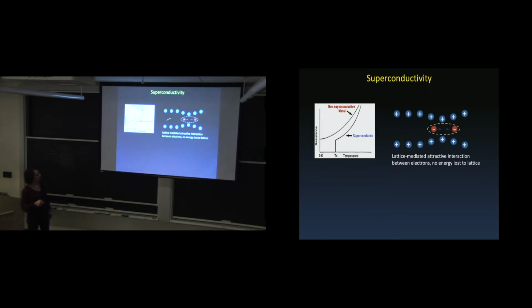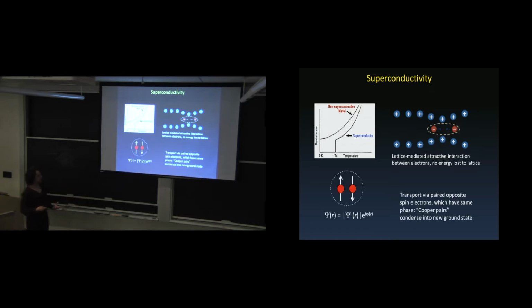And because it's mediated by the lattice over large length scales, the pairs can move basically independent of disorder that might appear in the rest of the system, which means that they don't scatter, which means they move without losing energy. It's dissipationless. It's actually a quantum phenomenon. These pairs condense into a real quantum ground state, which is characterized by an amplitude and a phase. And these are Cooper pairs, opposite spin electrons.